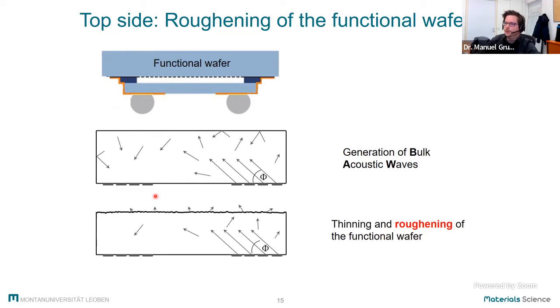So what manufacturers do is to thin and roughen the substrate in order to scatter away these unwanted bulk acoustic waves. And everyone who is familiar with brittle materials will know that introducing such defects into the surface will very likely decrease the strength of the material.